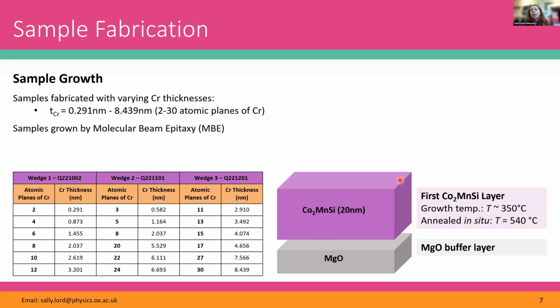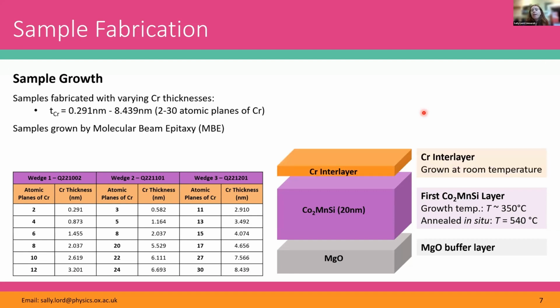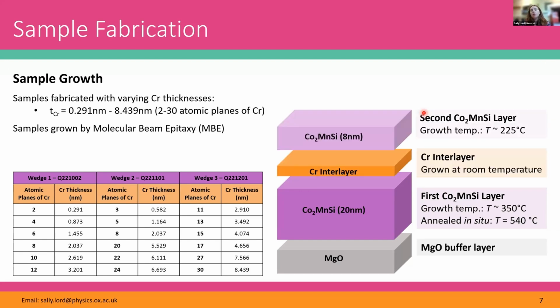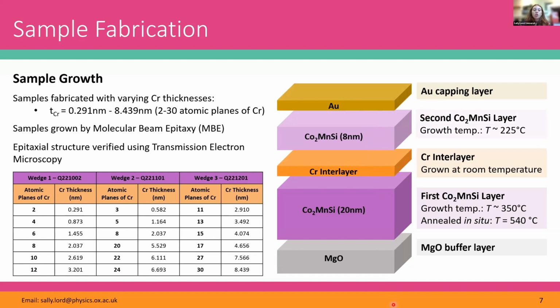Then the first cobalt manganese silicon layer was deposited at a temperature of 350 degrees and then annealed in situ to improve the chemical ordering of the Heusler. Then the chromium interlayer was deposited at room temperature. After this, the second cobalt manganese silicon layer was deposited at reduced temperature compared to the first, and this was to prevent interdiffusion between the cobalt, manganese, silicon, and the chromium. And then finally, a gold capping layer was added on the top to prevent oxidation. And the epitaxial structure of these samples was verified using transmission electron microscopy measurements.